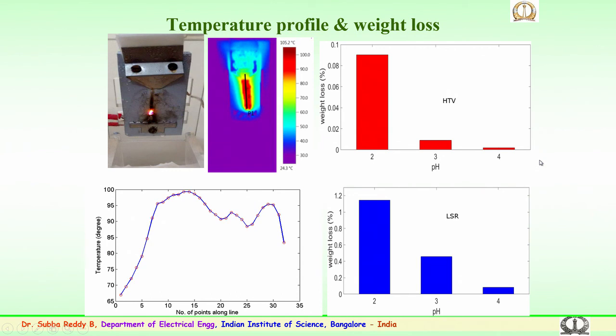During the process, experimentation has been conducted for 3 to 6 hours continuously, and the sample performance has been monitored. The level of surface degradation and the erosion which takes place during the application of voltage has been continuously monitored, both electrically by measuring the leakage currents, and also by using a thermal imager to find out the temperature properties, that is, temperature changes on the entire surface during the voltage application.